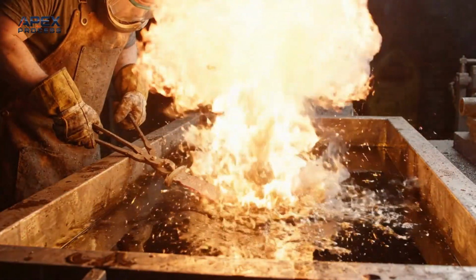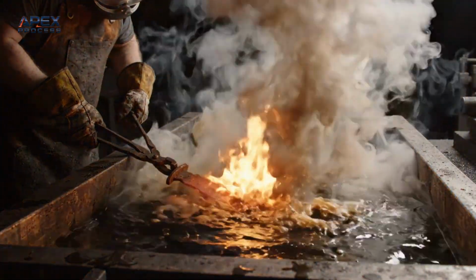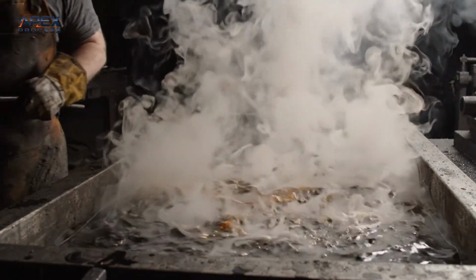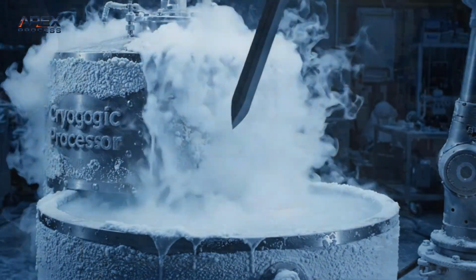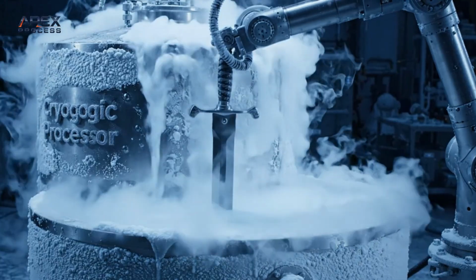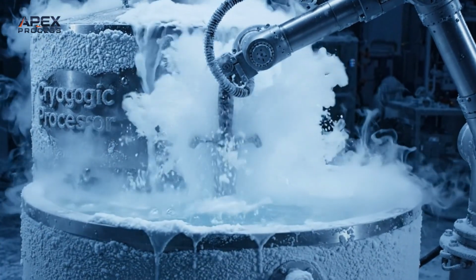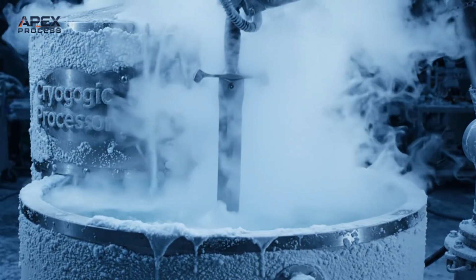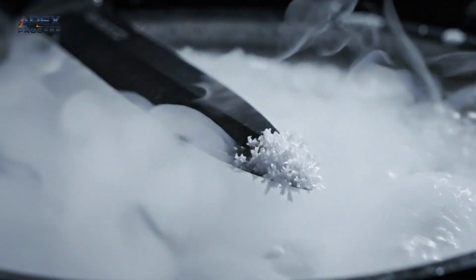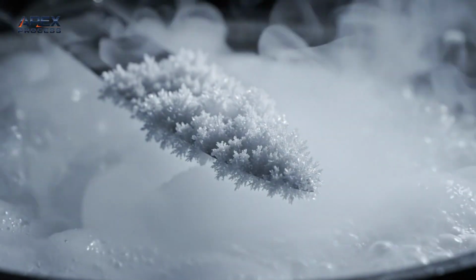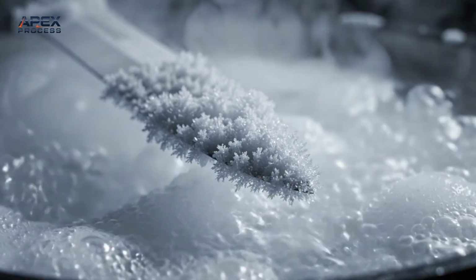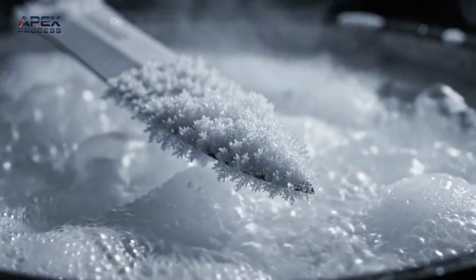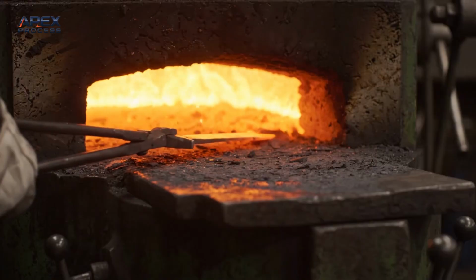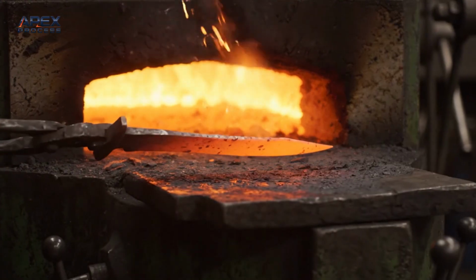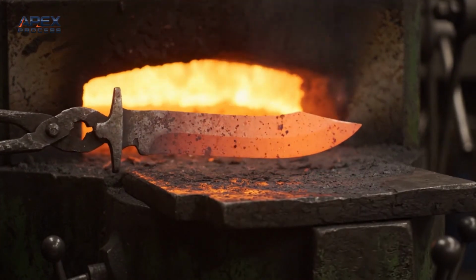Quenching. Rapid cooling traps the carbon atoms, turning the steel into a hard, martensite structure. Cryogenic treatment. We submerge the blade in liquid nitrogen at -196 Celsius for 24 hours. Deep freezing converts the remaining austenite into martensite, maximizing edge retention. Tempering. We sacrifice a small amount of hardness to give the blade vital toughness and flexibility.